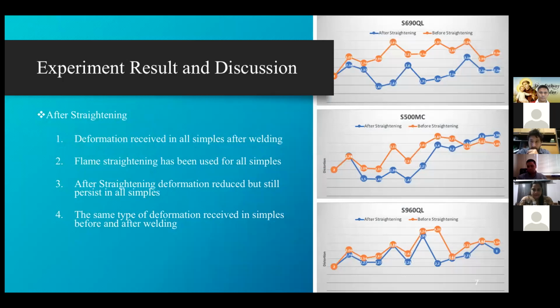After the welding, we applied flame straightening for all our materials, and as we can see in those graphs, the deformation has been reduced in all of them, but it persists. As we can see also, the same type of deformation, bowing deformation, was observed for all of them. The next step is to check the microstructure after flame straightening for all of our materials.